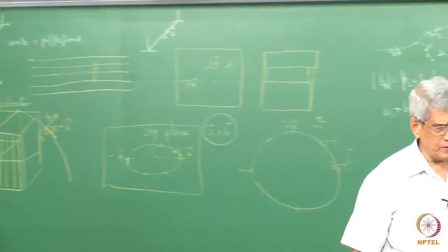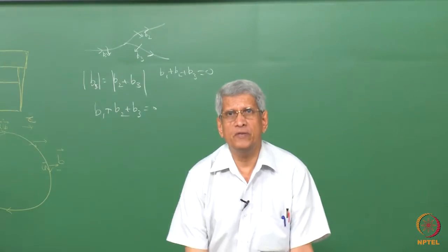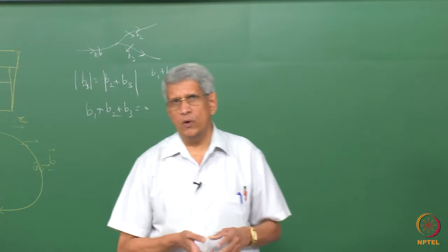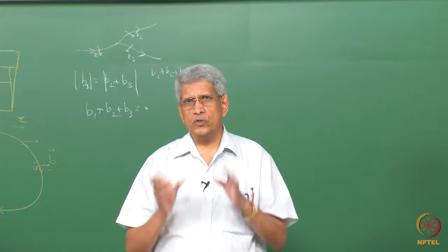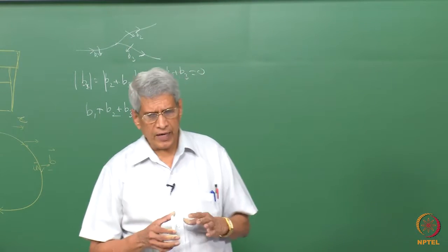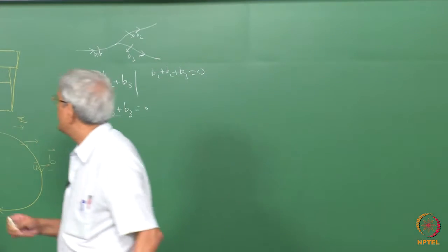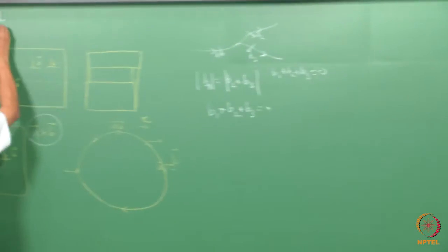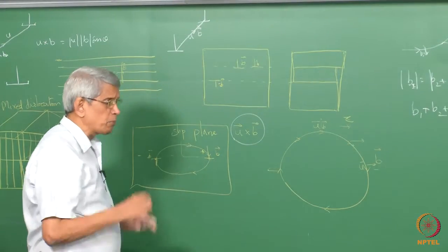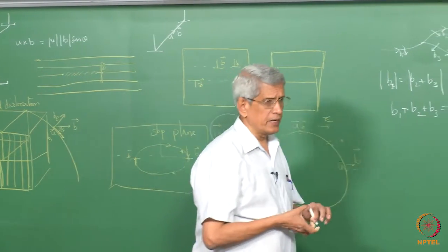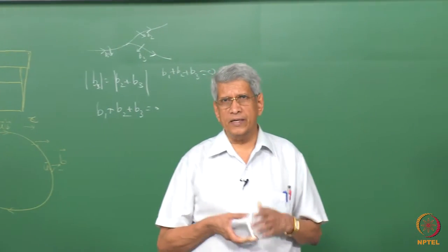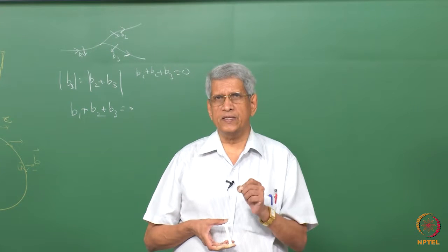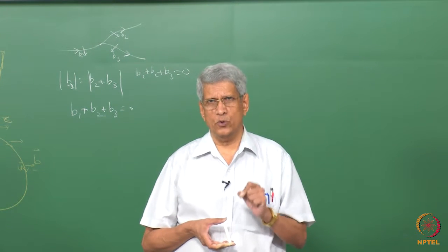That means in this specific case no slip plane is defined; any plane which contains this dislocation line is a potential slip plane. The dislocation can move on any of these planes. Then what dictates on which plane this screw dislocation will move?